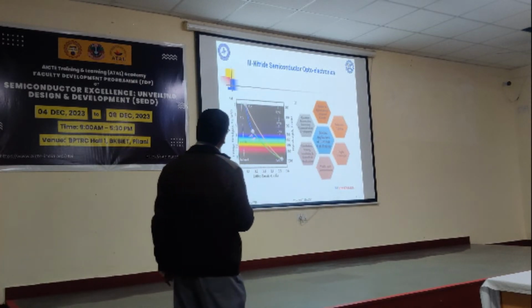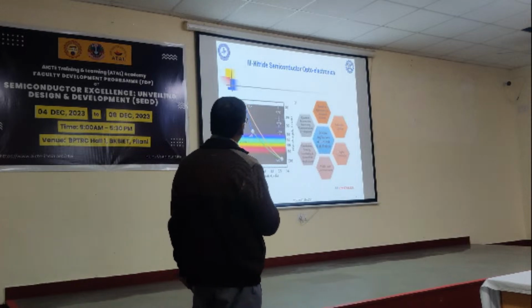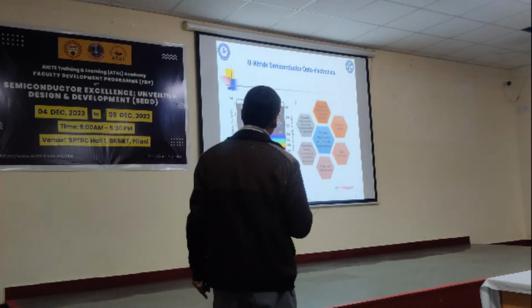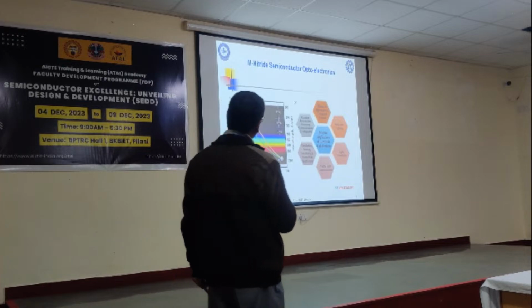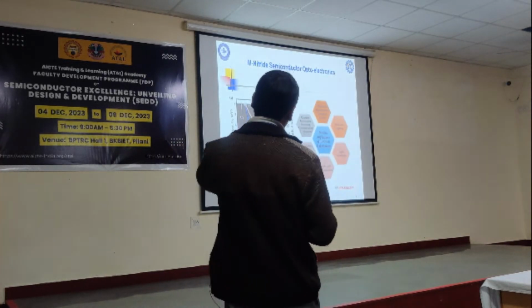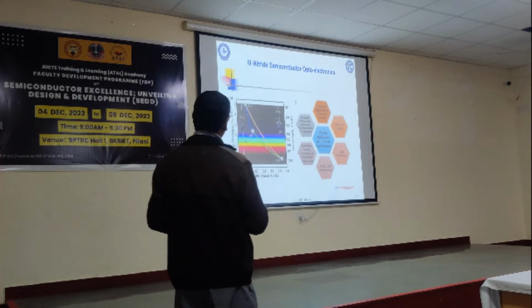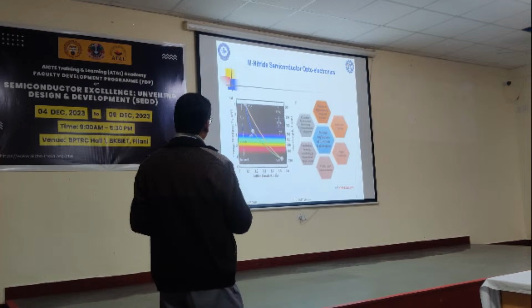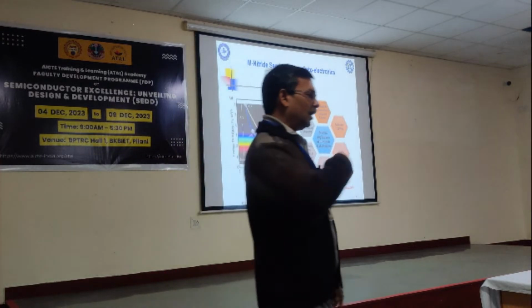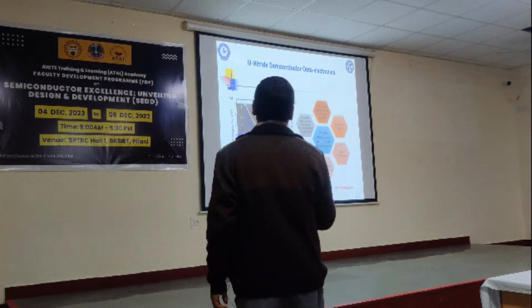So here, gallium nitride is the base material, and we can introduce aluminum composition as well as indium composition. Gallium nitride is a binary semiconductor with two elements, but if we incorporate aluminum in the composition, it will be AlGaN. So a certain composition of aluminum will be there in gallium nitride. What will happen? Gallium nitride has a certain band gap. Here we see the lattice constant of that semiconductor and the band gap. Gallium nitride has a band gap of around 3.4 electron volts. But if we incorporate aluminum, the band gap of this material can change up to 6.1 electron volts.